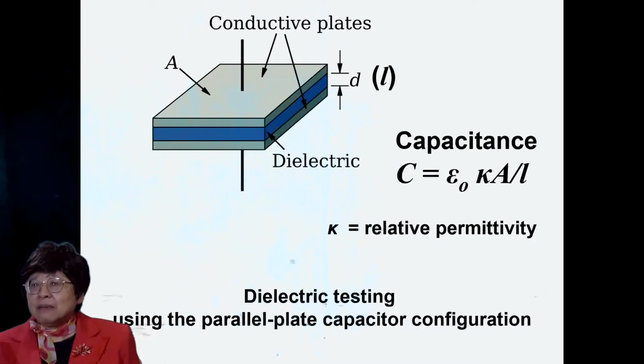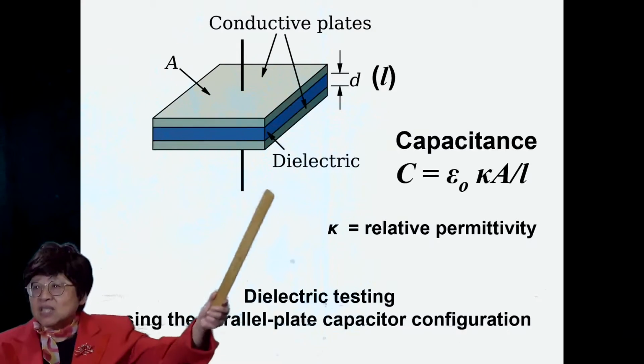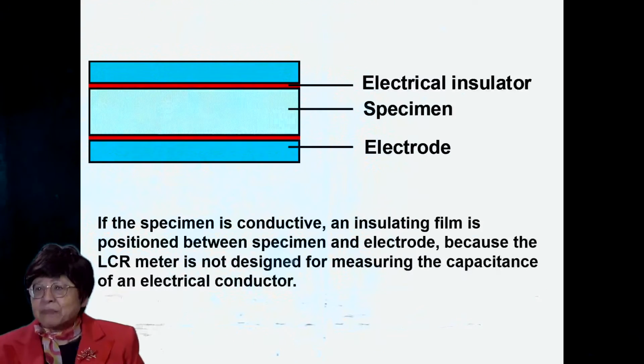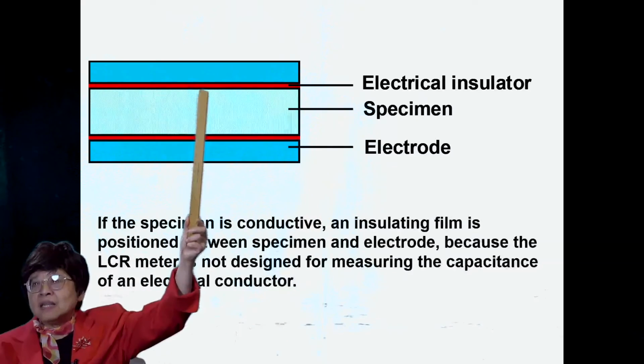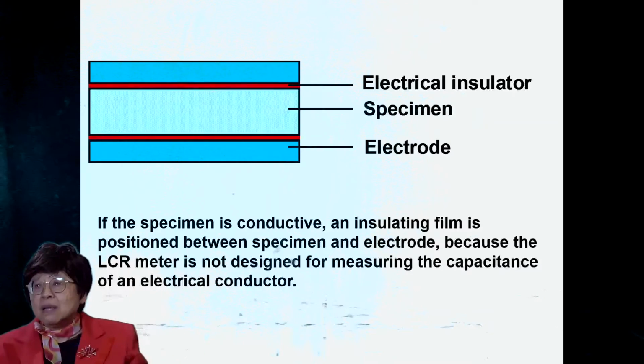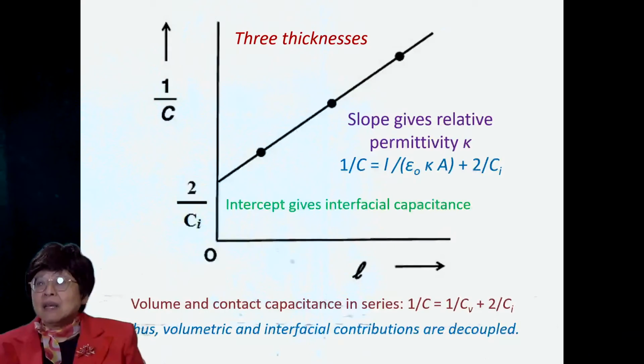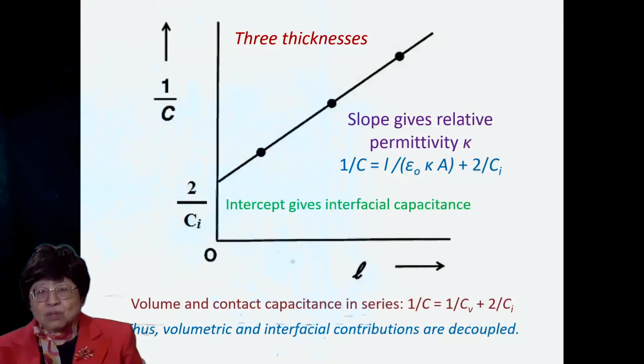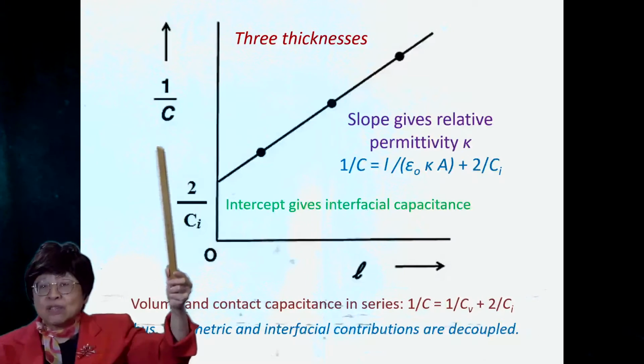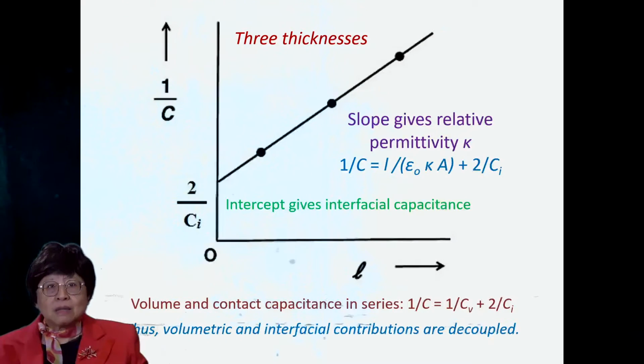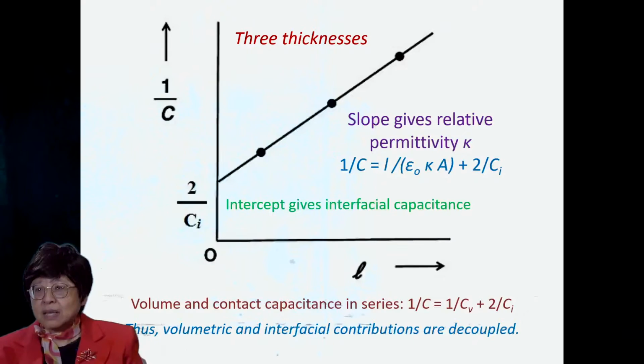Now, dielectric testing involves parallel plate capacitor configuration, and C is the capacitance, kappa is the relative permittivity. But for a conductor, one needs to be careful because an LCR meter is not designed for measuring the capacitance of a conductor. So one needs to put in a thin insulating film between the specimen and an electrode in order to make the LCR meter behave. And one can decouple between the capacitance due to the specimen and the capacitance due to the interface by measuring the capacitance C at 3 or more different thicknesses and plotting 1 over C because this is a matter of capacitors in series, and the slope relates to the permittivity. And so we can decouple between the capacitance due to the specimen and the capacitance due to the interface.